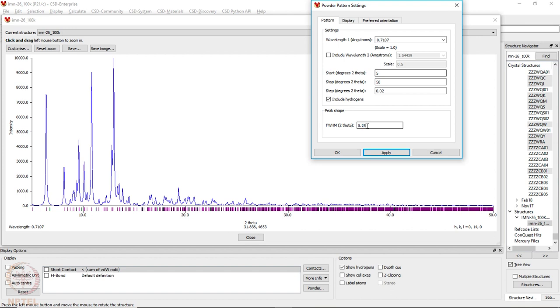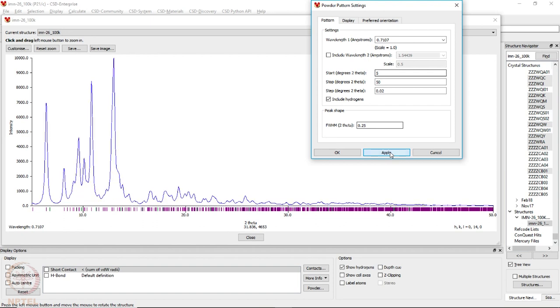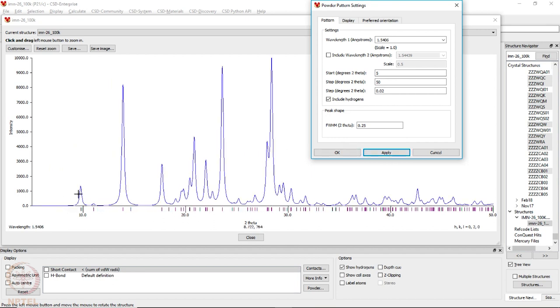So, by default you will have the FWHM about 0.25 degree in 2 theta and you will get a more featureless, or rather merged, powder X-ray diffraction pattern using molybdenum radiation. But the same if we use copper, 1.5406 angstrom wavelength, and then we apply it, you see that the peaks are well spread, they are not merged, and with the same FWHM there are several peaks which can be distinguished from the others. With molybdenum, all these peaks completely disappeared or merged together.